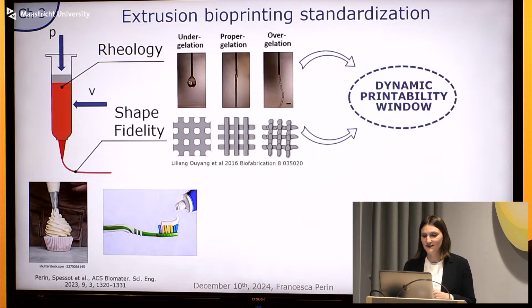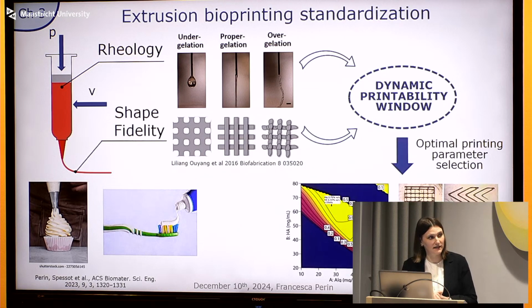So we decided to work on building empirical models on both rheology and shape fidelity of a series of inks. By applying constraints, we found a printability window. And with the models that we created, we optimized printing parameter selection and also the composition of our ink by applying a function with the desirable values that we wanted for the shape fidelity.